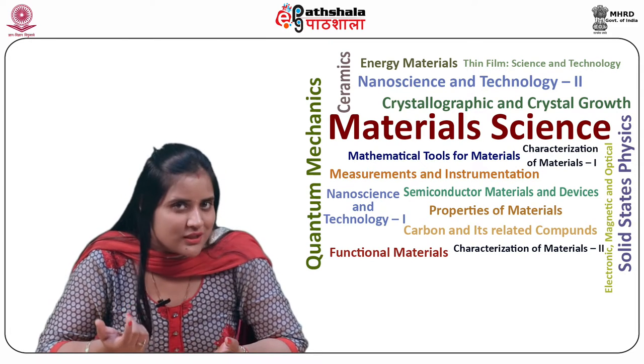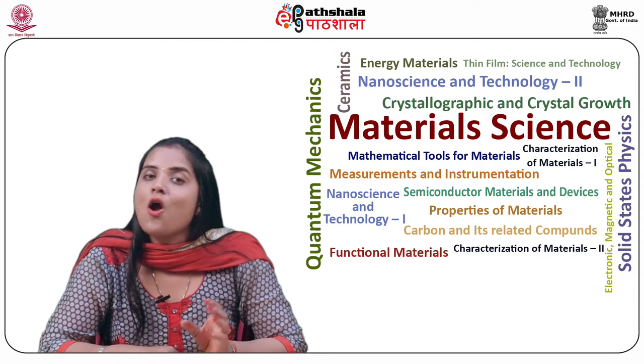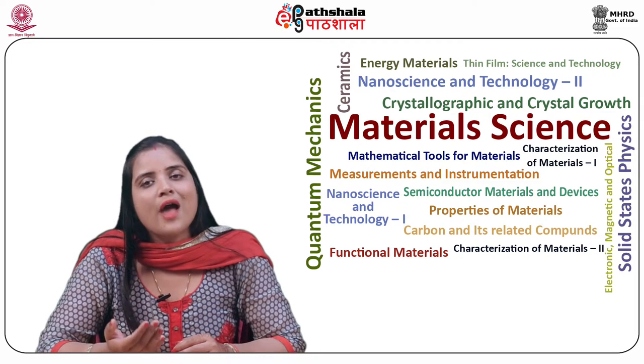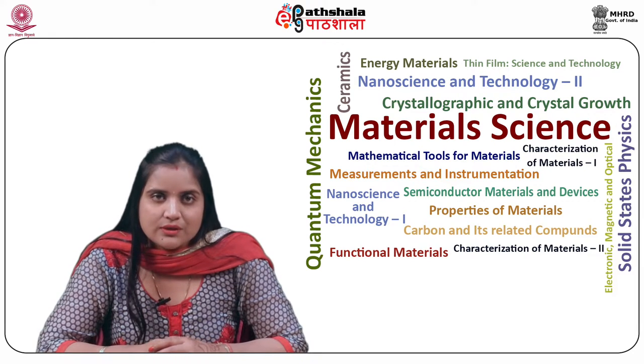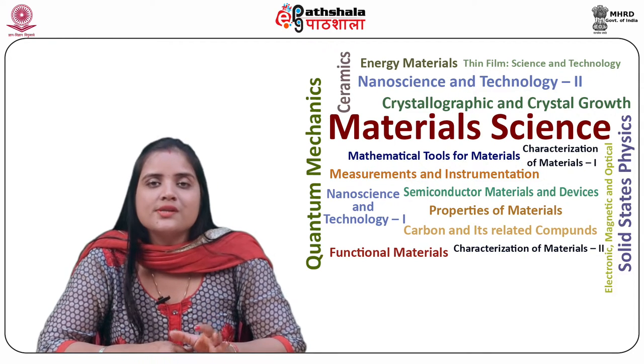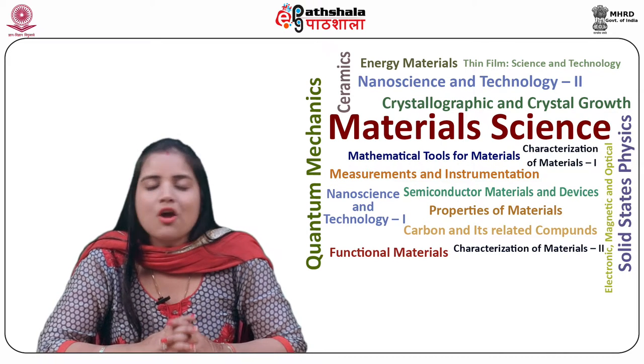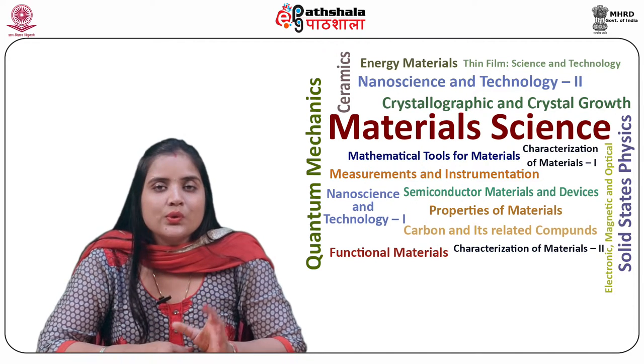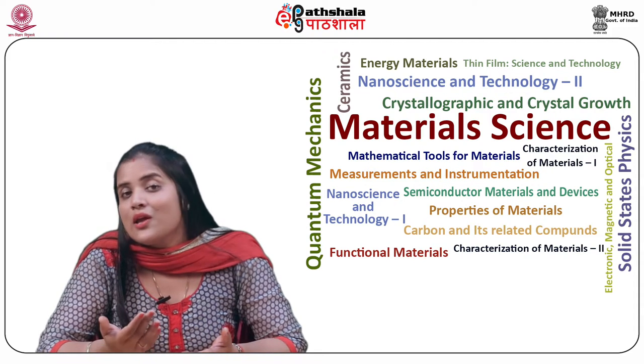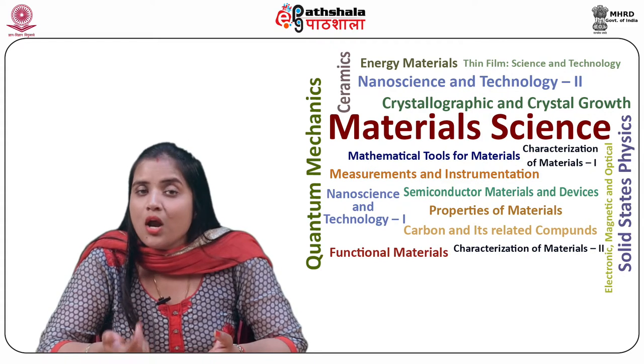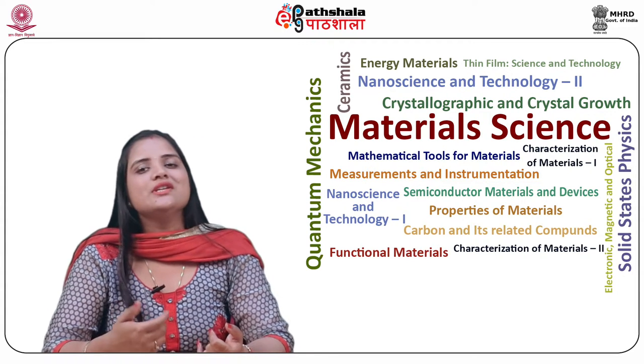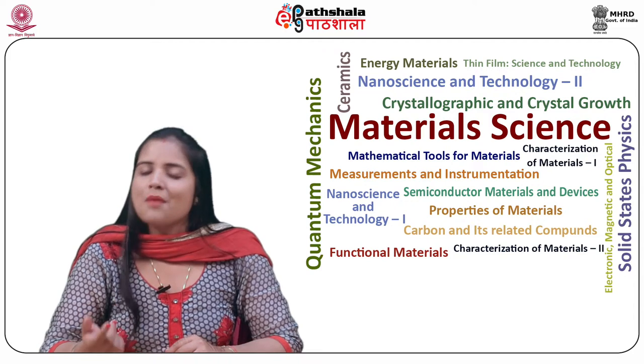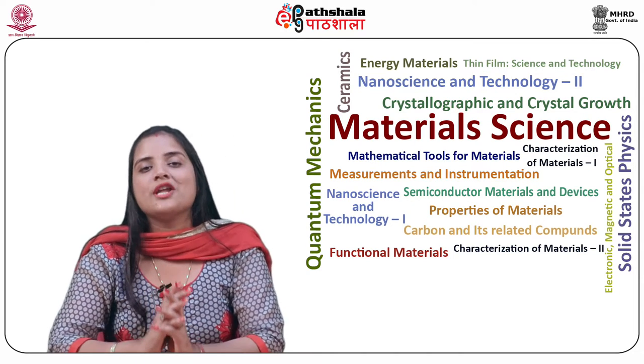Coming on to epitaxial silicon. Epitaxial wafers of crystalline silicon can be grown over a monocrystalline silicon seed wafer via chemical vapor deposition process. After growth, these wafers are detachable as self-standing wafers of controlled thickness. The efficiencies of solar cells produced from these wafers are comparable to that of wafer-cut cells. However, they are much cheaper when CVD is performed at atmospheric pressures. The light absorption can be enhanced by tailoring the surface of epitaxial wafers.